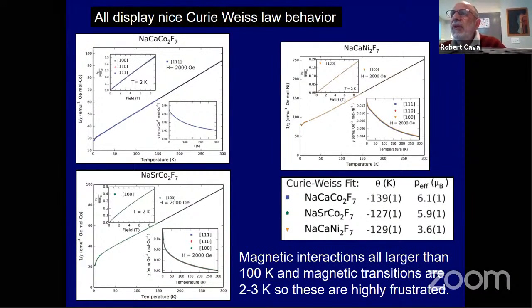And so this, when you plot 1 over the susceptibility versus temperature, if you get a straight line, which you get here, let's look at this one. You get a beautiful straight line, and then at low temperature, something strange starts to happen. And that's an indication of, first of all, the intercept of this line tells you the interaction temperature. And then this temperature right here tells you that's when the spins are starting to do something and make them deviate from the Curie-Weiss law.